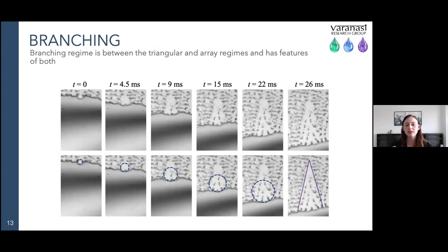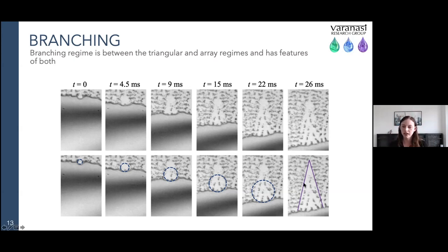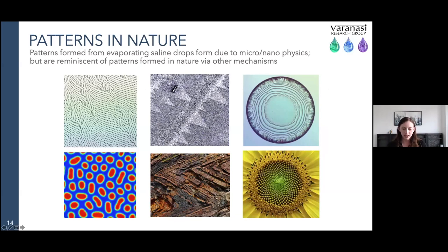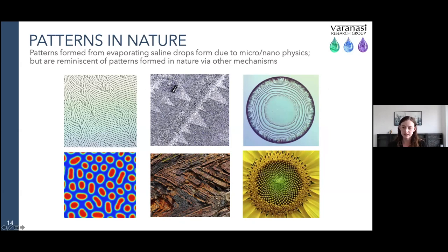Finally, there's the branching regime, which I believe is a mixture of both regimes, having features of both. You can more readily see what's happening using the branching regime because the contact line is a little thicker and the instability is also a little bit larger — almost like a circle that's expanding, except when you pull a circle in one direction, it forms a triangle. These patterns are observed throughout nature: periodic arrays in reaction-diffusion patterns, triangular patterns in geology, and spiral patterns are also observed.